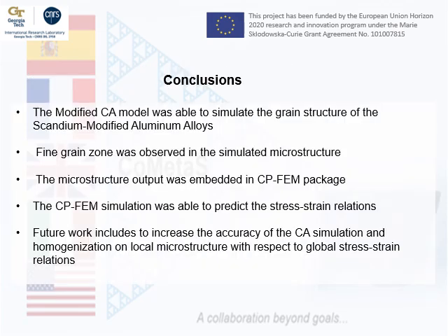results. Okay. To conclude, we utilized here the cellular automaton model to simulate the grain structure of the scandium aluminum alloy. We observed the fine grain and also the columnar grain. The microstructural output was coupled with crystal plasticity finite element simulations, and we were able to predict the mechanical properties of the material. Right? So future work includes improving the accuracy of the crystal plasticity simulations and also the cellular automaton.